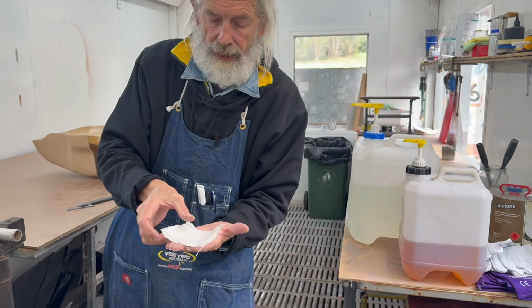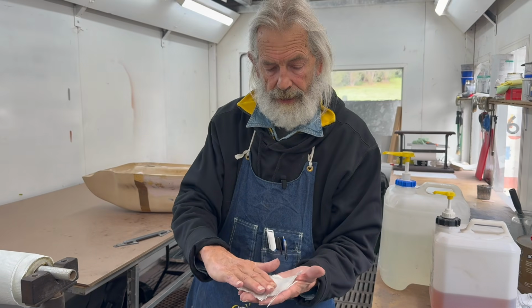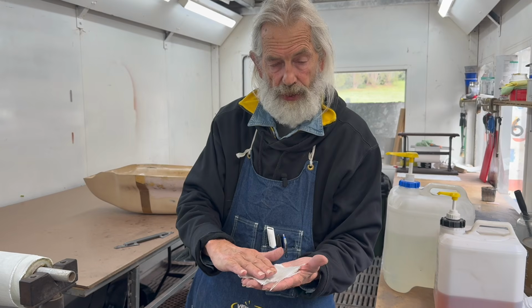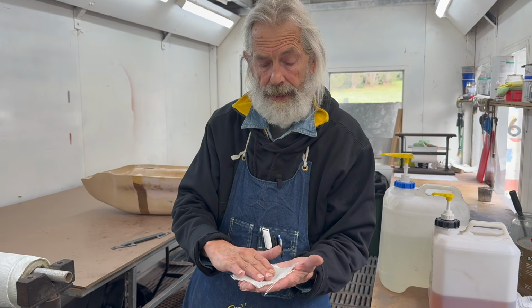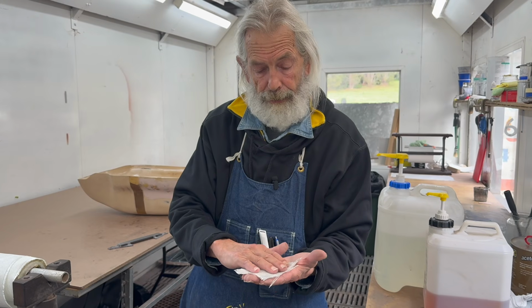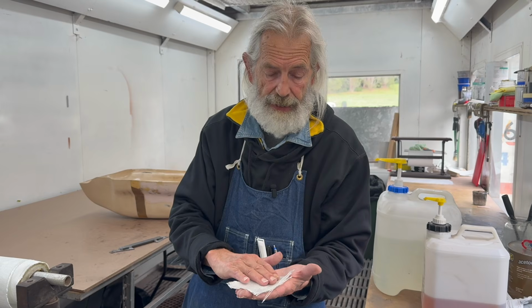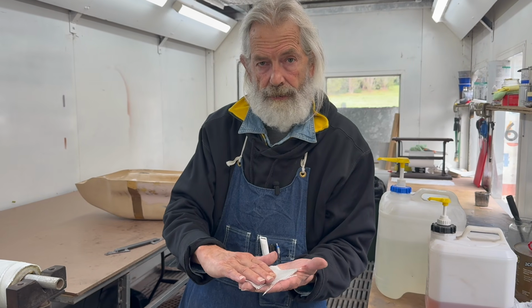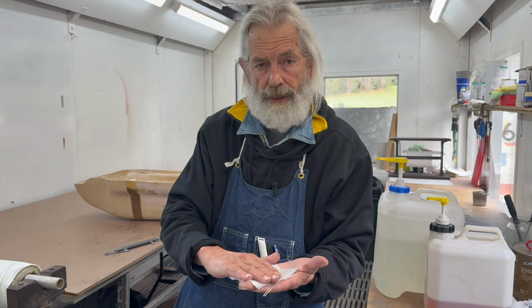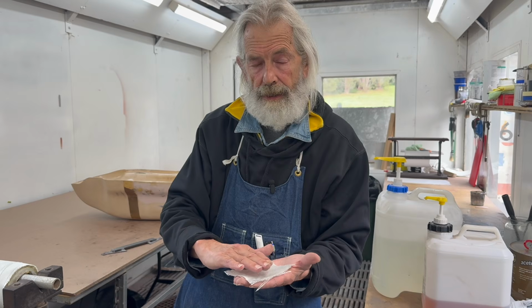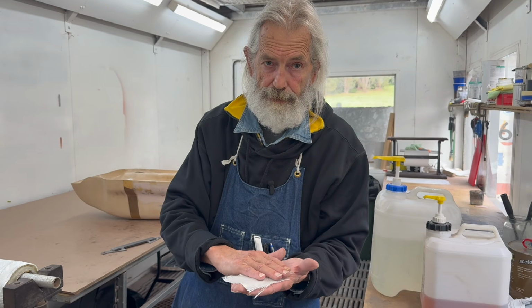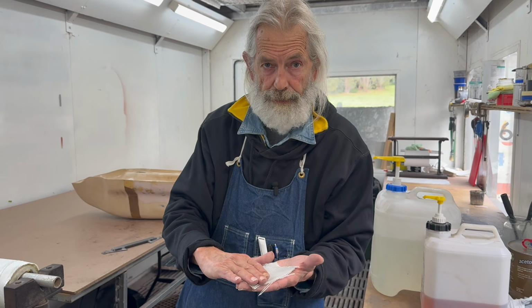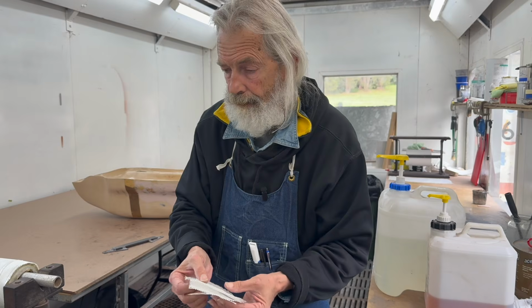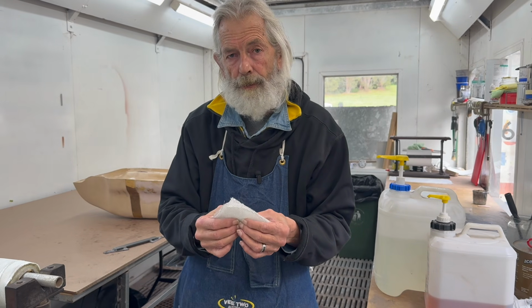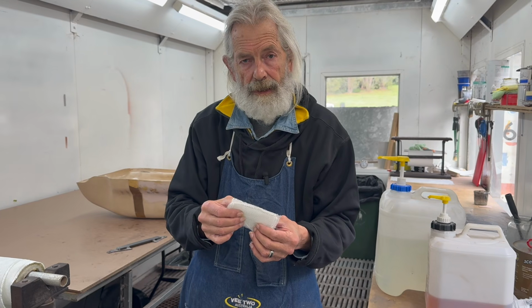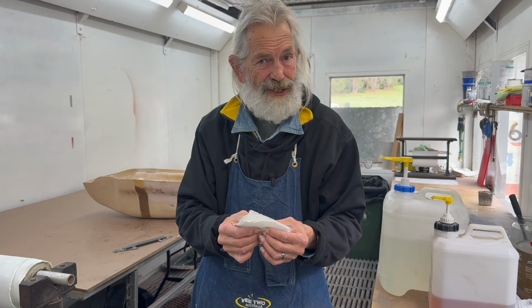So this is the fabric that we use, and we build up the layers. Where it's necessary to have more strength, we can include more layers. For example, around a bolt hole, we would use double the number of layers. It also controls the resin content, and we can get very close to the optimum fiber to resin content, which is about 60% fiber and 40% resin. That makes the part an optimal weight to strength, and that's why we call it performance composites.